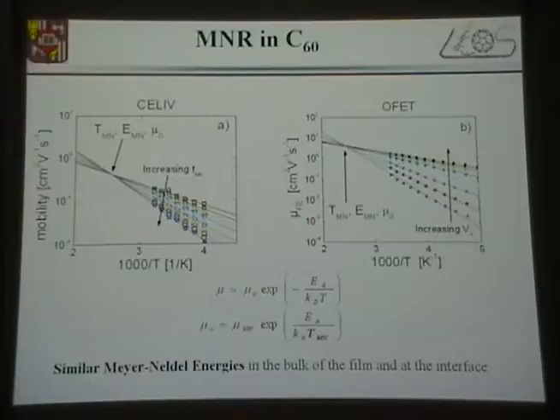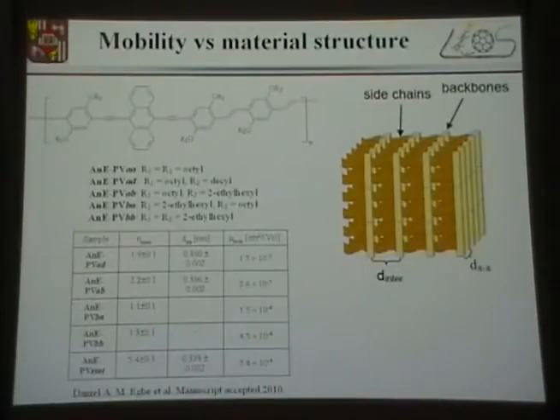So by getting this energy or this temperature, we're able to comparatively compare the Meyer-Neldel energies from CELIV, which is the measurement of mobility in the volume of the film. We compare this to the OFET measurements, which is the transport at the interface between the semiconductor and dielectric. And surprisingly, in the inert materials, we use the BCB dielectric, which is completely inert, there's no polar interfaces, nothing. We got a similar level of disorder. This energy was around 45 millielectronvolts or so. But again, I'm not going into details about that.